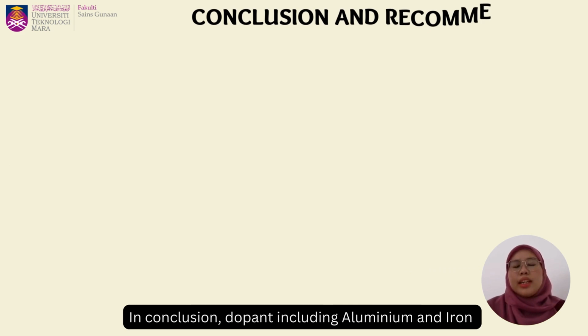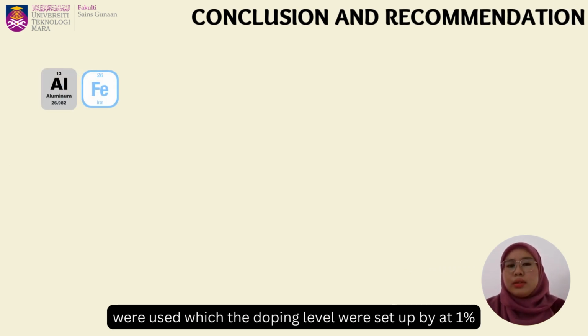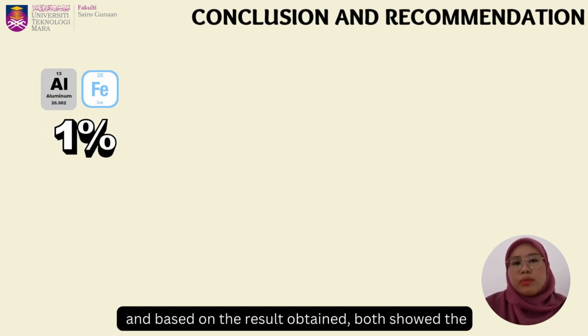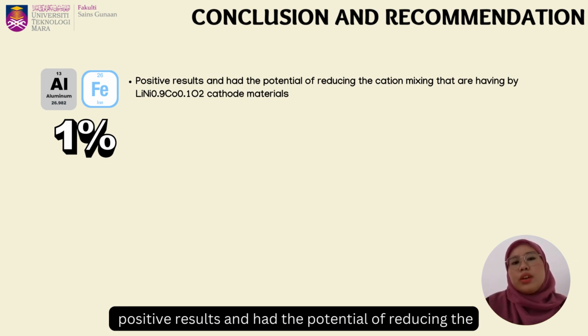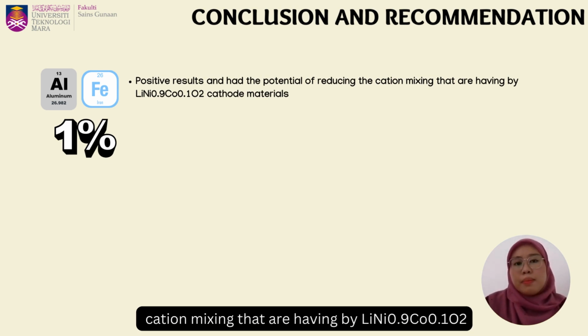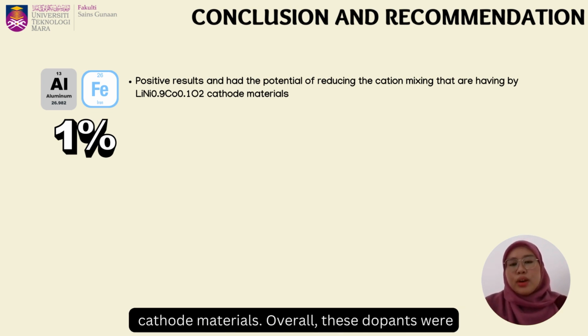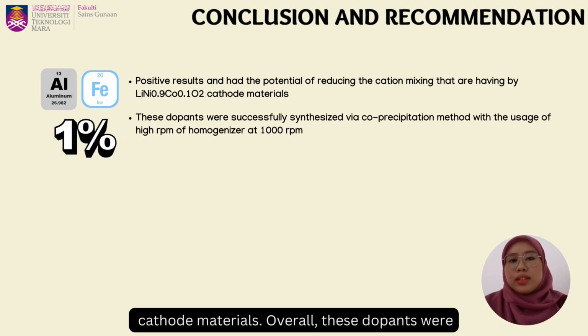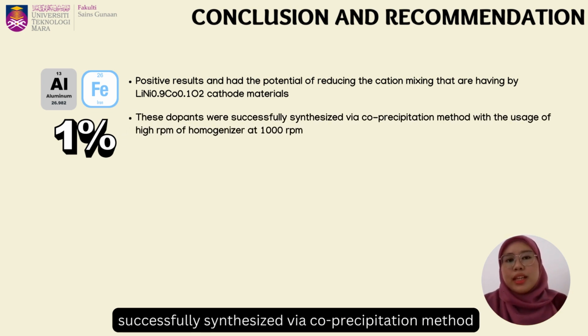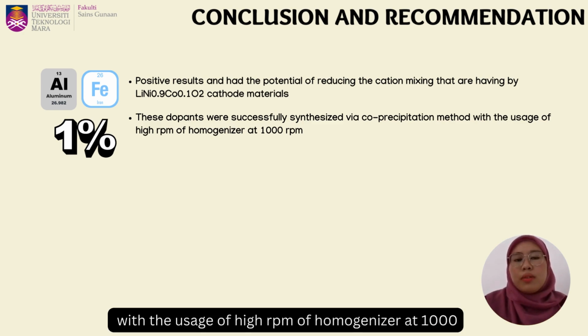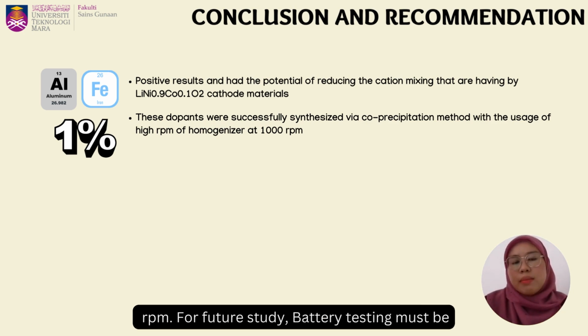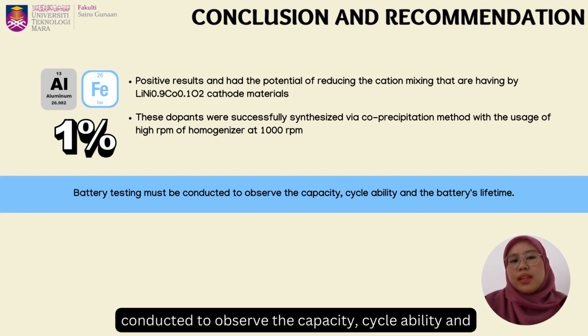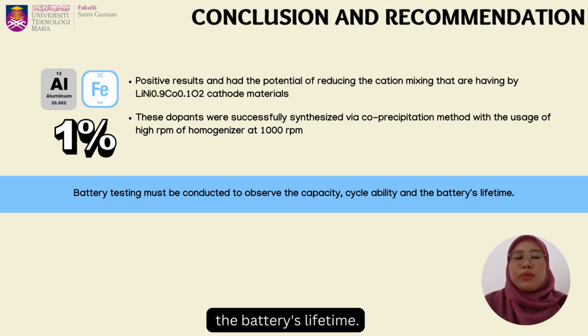In conclusion, dopants including aluminum and iron were used, with the doping level set at 1%, and based on the results both showed positive results and had the potential of reducing the cation mixing that is present in nickel-rich lithium nickel cobalt oxide cathode materials. Overall, these dopants were successfully synthesized via the co-precipitation method with the use of a high-RPM homogenizer at 1000 RPM. For future study, battery testing must be conducted to observe the capacity, cyclability, and the battery's lifetime.